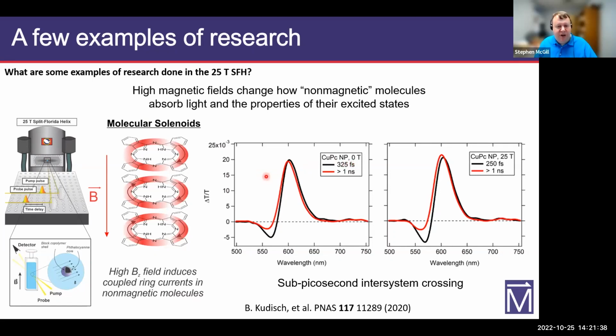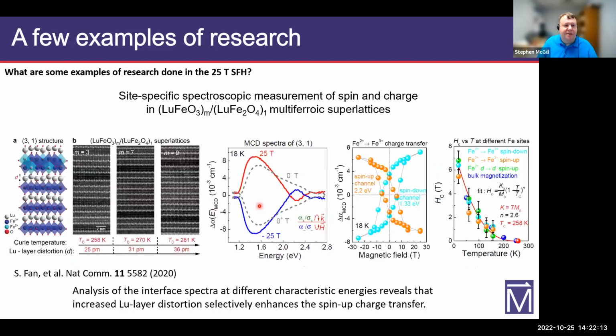black being 325 femtoseconds after the excitation pulse. And then here we have the same measurement at 25 Tesla, the black one being very different relative to the data at very, very long times, which is a sign of the relaxation back to the steady state. And it has changed that behavior there. And so these systems are often considered as platforms for spintronics or quantum computing. And so this gives us an understanding of the charge dynamics that are happening on short time scales in these materials. Now, here's a completely different example that is done by Jan Musfeldt's group.